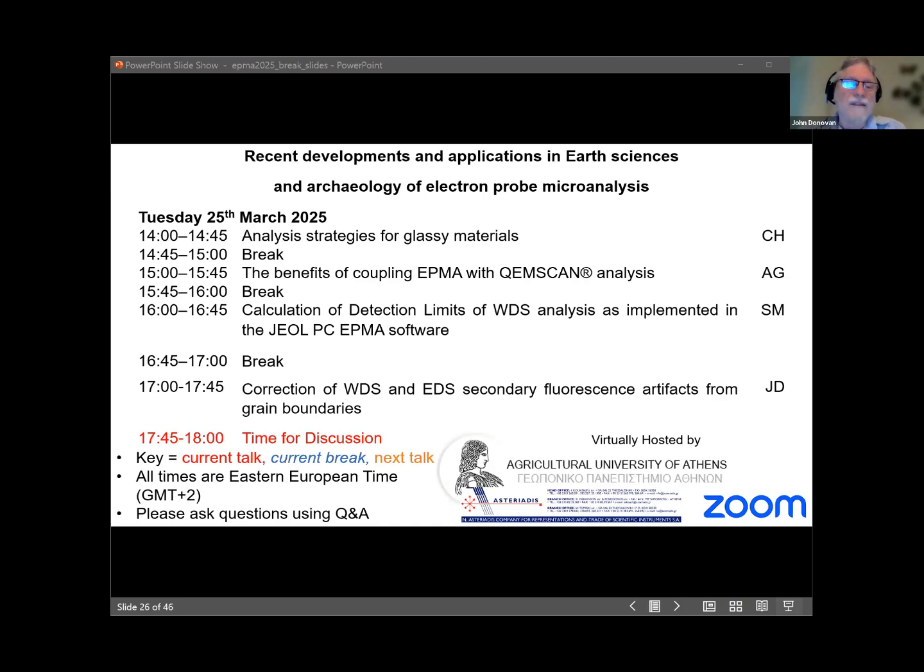In fact, this work was kind of instigated about 10, 15 years ago, when we had a student who was trying to analyze titanium in quartz, Marissa Acosta, who did a great job on it. She was studying the thermodynamics of this because she wanted to know, like Annette mentioned, what temperature this quartz formed at, by measuring the titanium content in it. We knew about the secondary fluorescence problem, and one of the solutions she used was a FIB to carve out the grains, mount them on a TEM grid, and put them in the microprobe. So we had a TEM mount in the microprobe.